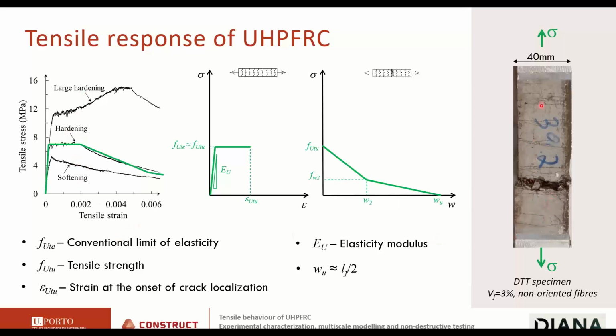And now look at the crack spacing. Now we see the cracks have a spacing of about, let's say, 15 to 20 millimeters. In this case, it's clear that the localization of the deformations occurred while the specimen was still in the crack formation stage. More cracks could form if localization didn't stop the process.